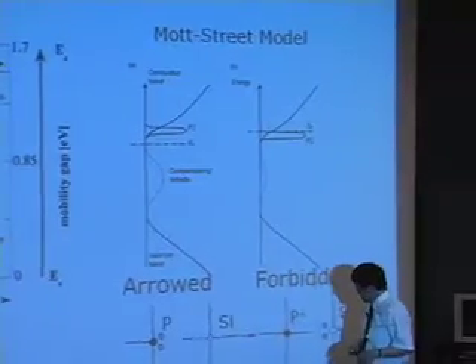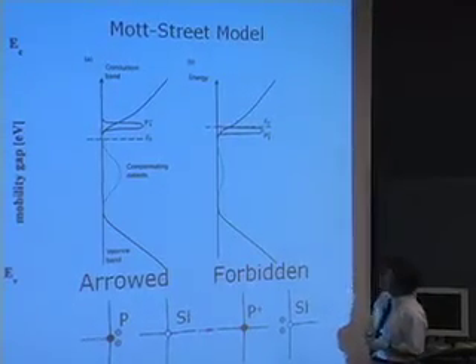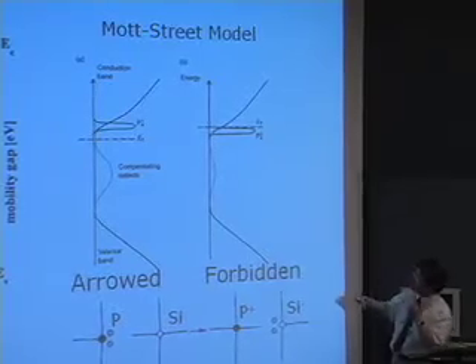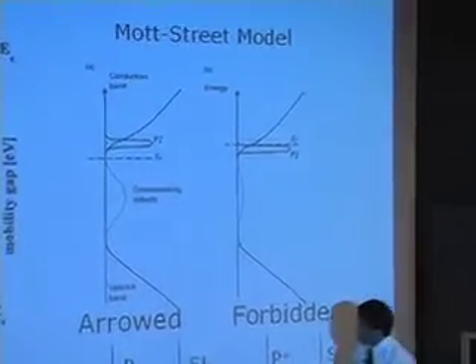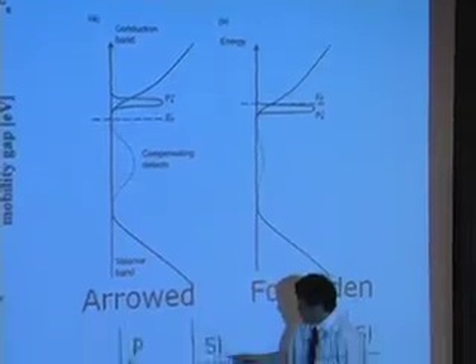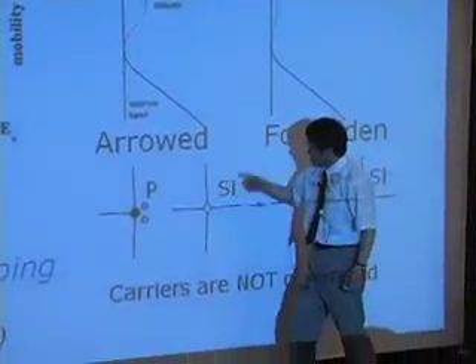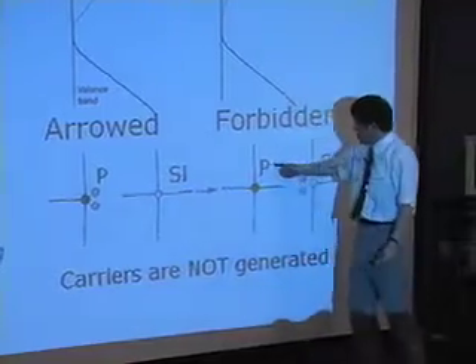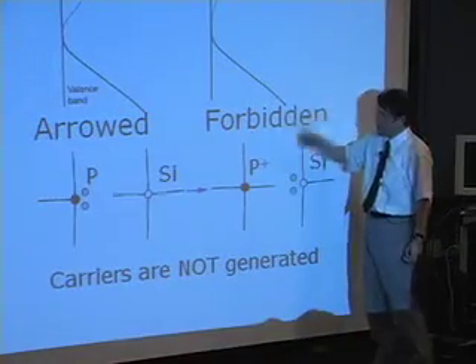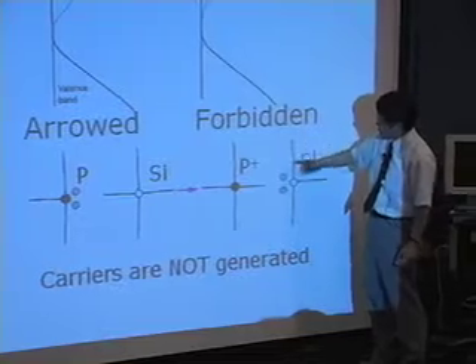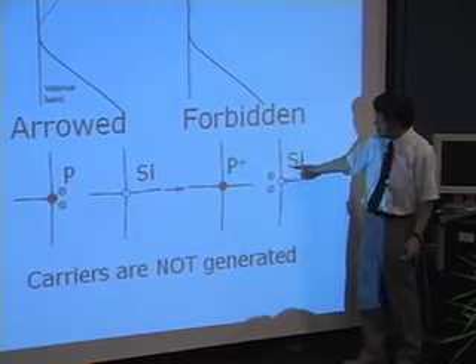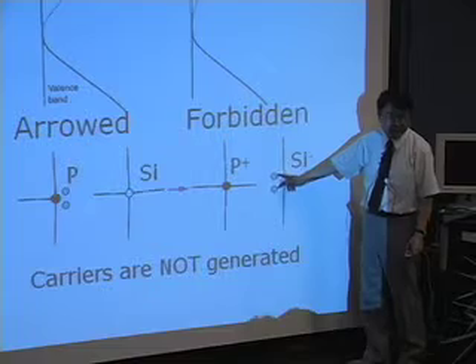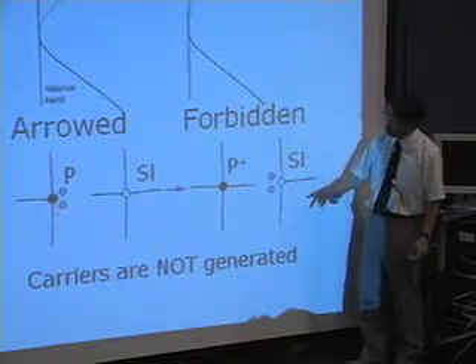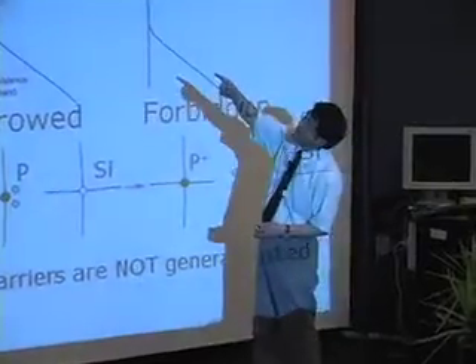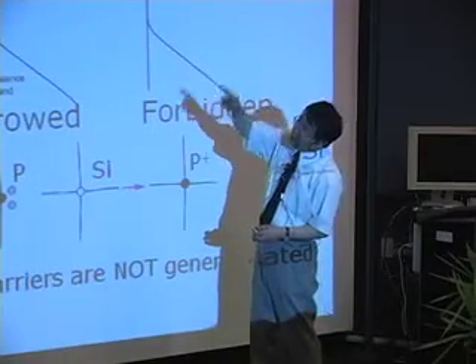To explain this, Bob Street of Xerox presented a model. When phosphorus is doped, the phosphorus ion replaces a silicon site, and its electron is generated. But the generated electron is again trapped at a silicon site as a lone pair. This means that self-compensation occurred. That's why the Fermi level cannot exceed the mobility gap.